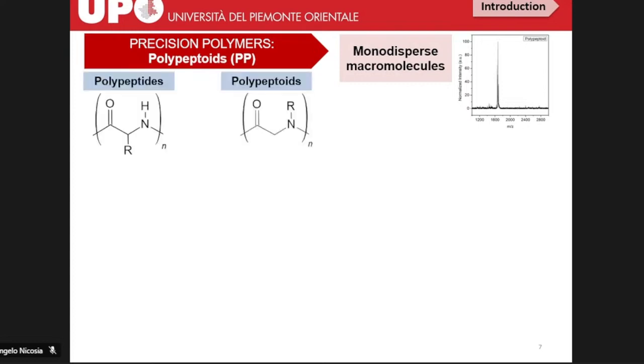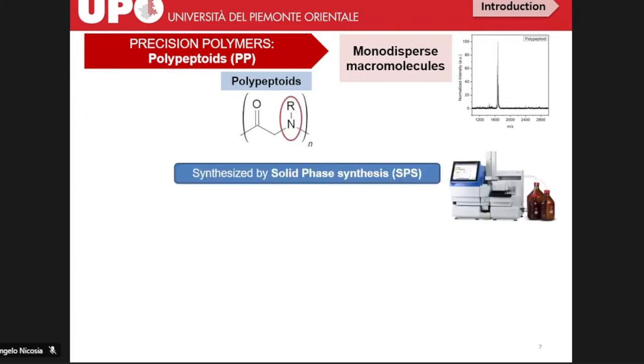And the approach that we are taking is by using polypeptoids. These are molecules quite related to polypeptides. The difference is that the substitution is on the nitrogen instead of the alpha carbon. This structural characteristic makes them soluble in organic solvents as they cannot form hydrogen bonds. On the other side, they can be synthesized by solid phase synthesis. The difference is that we are not using amino acids as units, but we are using submonomers.